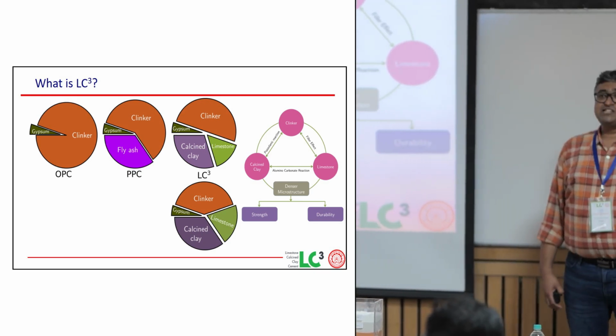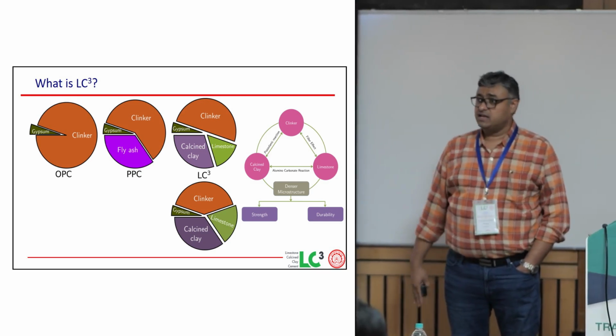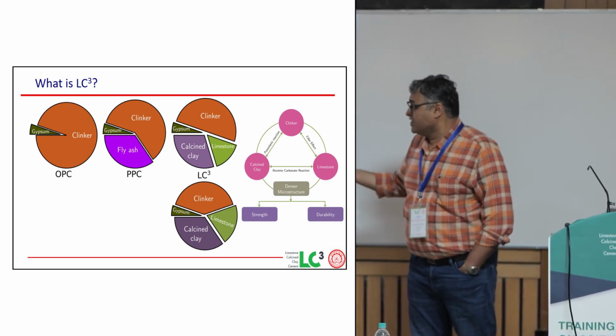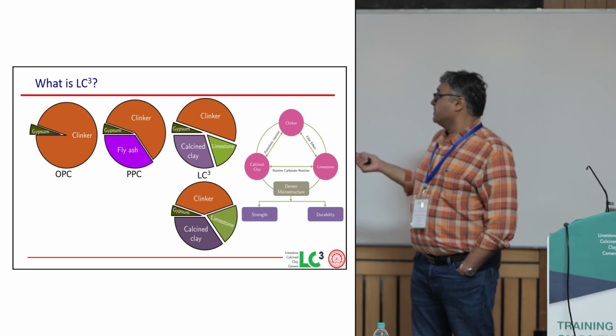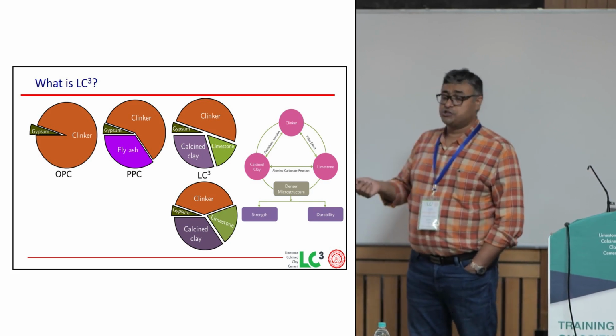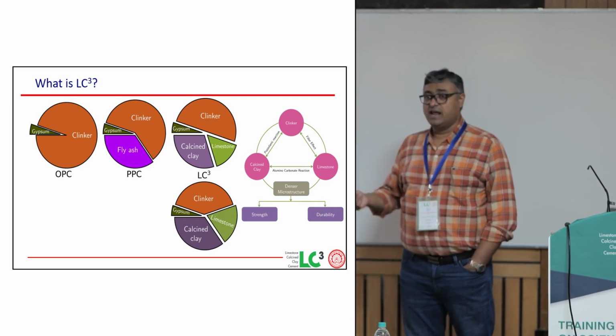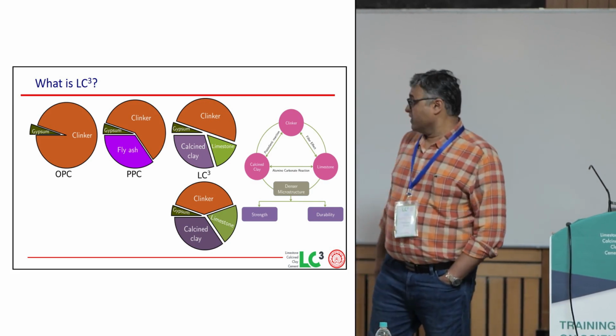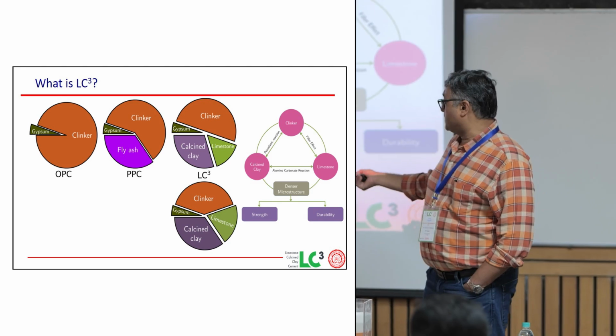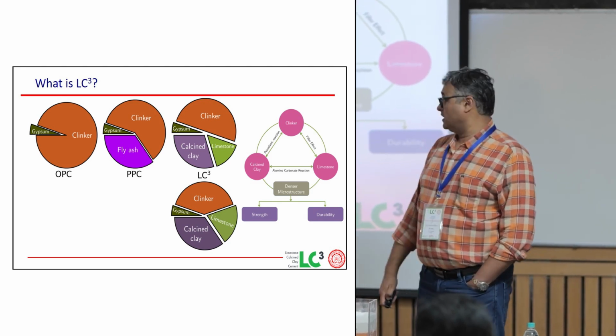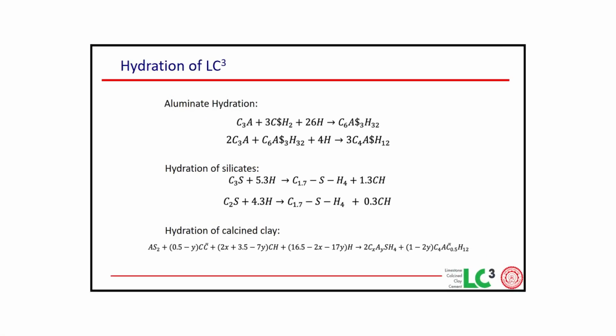But the idea of LC3 is that you can bring down the clinker content at least to 50% and even lower, and still manage to get a dense microstructure because the clay, the limestone, and the clinker are all reacting with each other. The biggest advantage comes from the limestone reacting in this particular case, as I'm going to explain to you in the next slide.